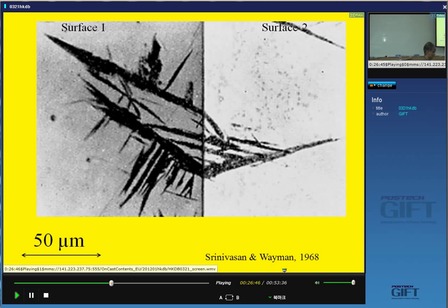And the importance of this, so this is again bainite, and it's partially transformed to bainite. So this is bainite, this is all martensite. You can see that the bainite is plate-shaped in three dimensions. So it's not a needle, it's not acicular. Acicular means needle-like. Needle-like is like this. It's a plate in three dimensions. Can you tell me why the bainite etches darker than martensite?